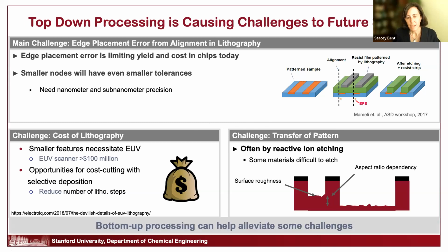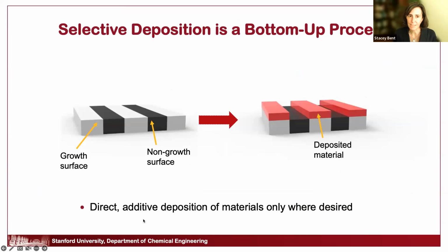And this motivates a new approach to fabricating the different layers. And this is called bottom-up processing. In particular, this is selective deposition. So if you imagine you have your underlying pattern in one of those multiple layers in a chip structure, could we deposit the material just where we want it? And we call the desired region the growth surface and the undesired region the non-growth surface. And so this is direct additive deposition of material only where desired.